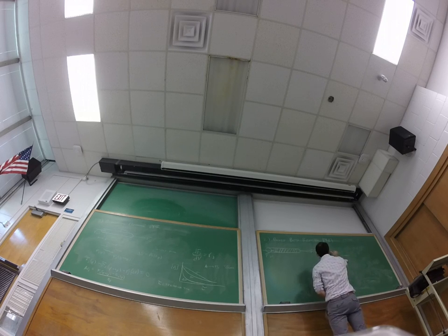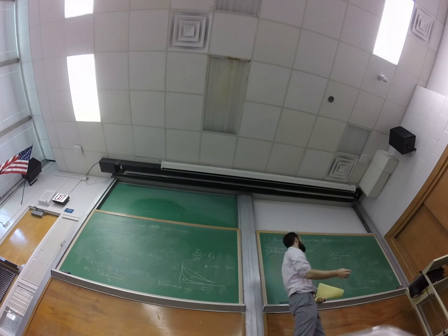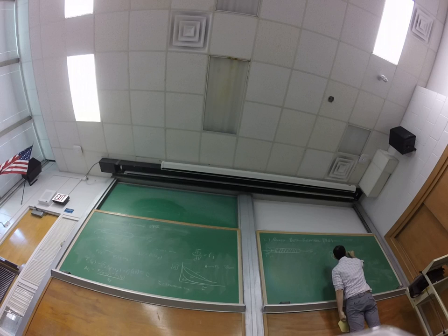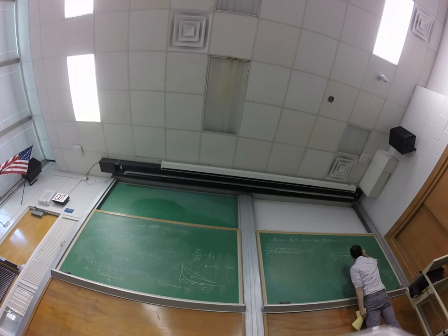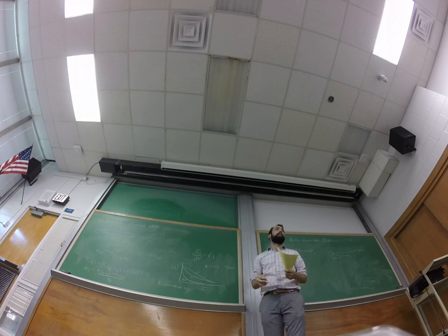And then often you'll have that mixed with support that has no metal loading. So you'll already take a material like this, might be 1% platinum on alumina, and you might mix it with 10 times as much alumina. Yeah?